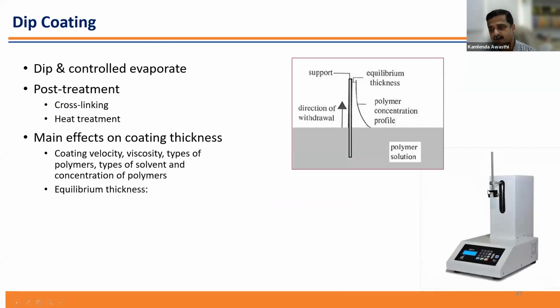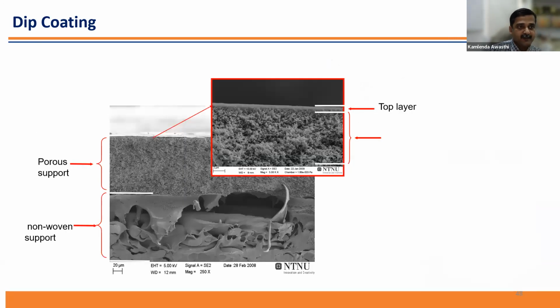So here you can see this dip coater. You can put your membrane, fixed here, and you can just dip it in a solution. So the dipping speed, dipping time, and the lifting speed basically decide the thickness of the coating on your membrane. Here you can see this is the porous support, and this is some non-woven support, and this is the top layer that you have coated over it.